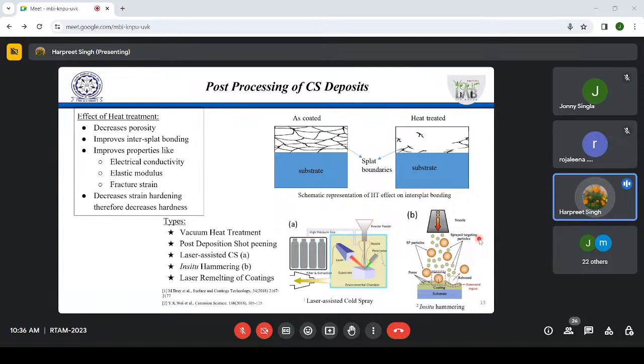Laser remelting is another approach, mainly to tailor the properties of upper layers only. When you do the heat treatment, the whole layer will get affected, right? But laser gives us the liberty to have effect only for the upper layers. For example, if you have a corrosion problem, you can mitigate the porosity in only the upper layers, right? By controlled exposure of the laser.